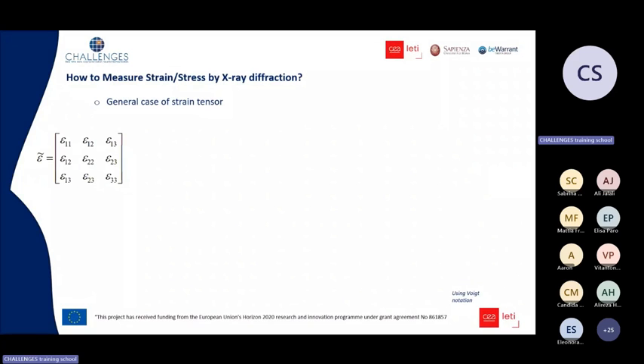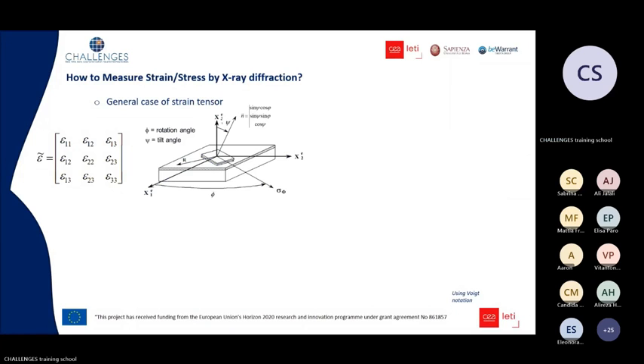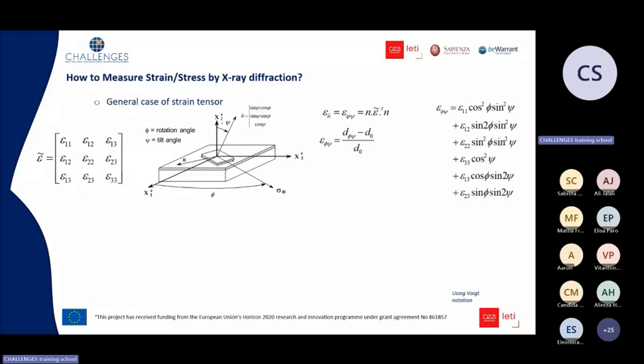And we can generalize this relationship to the general case of the strain tensor. So if now you have a general case of strain, with the six strain components of the strain tensor, and you look at one specific direction n defined by the angle phi, which is the angle in the plane, and psi, the tilt of the plane versus the normal to the surface. If you look at the strain in this direction, what we also call epsilon phi psi, this epsilon phi psi is defined by d phi psi minus d zero. If you do this projection using the strain tensor, we can define this strain versus the six components of the strain tensor, mixed, of course, with the phi and psi angles of measurement.